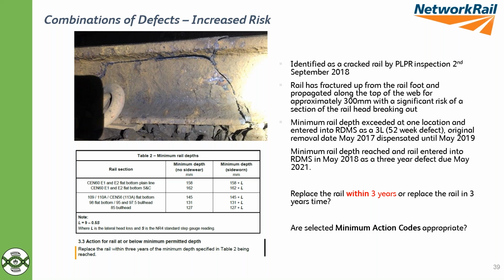Another example here where the rail, this one was picked up as a cracked rail, but virtually broken, or certainly broken by definition, but picked up by PLPR. But looking at it, we did pick it up originally. It was fractured along the foot, we had a minimum depth exceeded at one location. It was put in as RDMS as a 1-year defect. Unfortunately, that was dispensated out for a further 2 years to allow plans to re-rail it. Unfortunately, it broke in the meantime from that point.